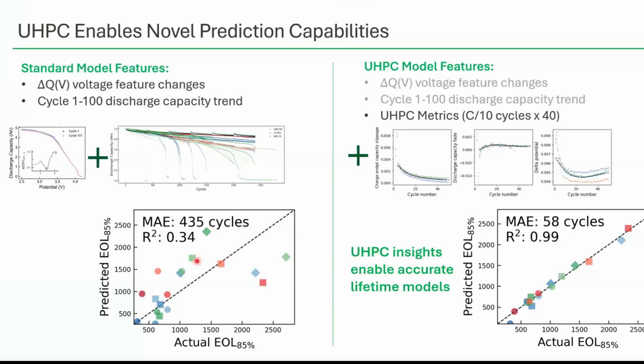A lot of the time these overpredictive states are because of these rollover failures that happen. If we work in UHPC model features, using those same early features, just looking at the first 100 cycles of the cycle aging data, and layering in charge endpoint capacity slippage, fade, coulombic efficiency, all as features in a machine learning model, the model tightens up almost immediately because we catch some of these overprediction cases. We also catch some of the underprediction with capacity fade and impedance information, and get really nicely performing lifetime prediction models.